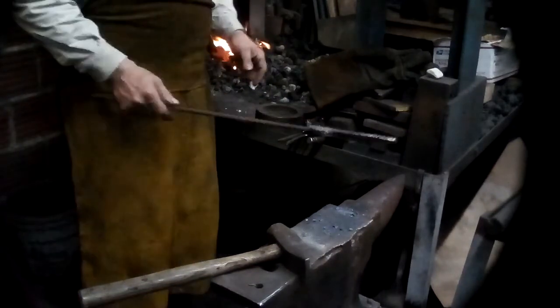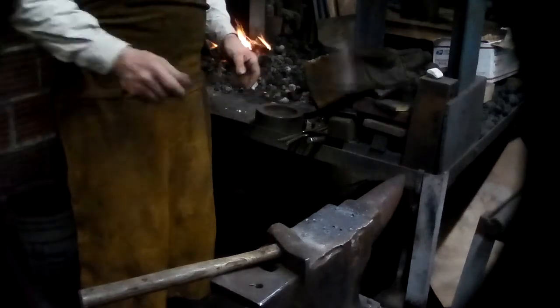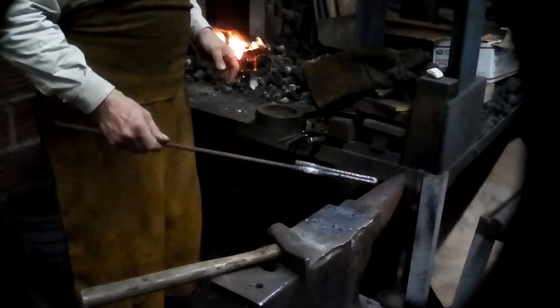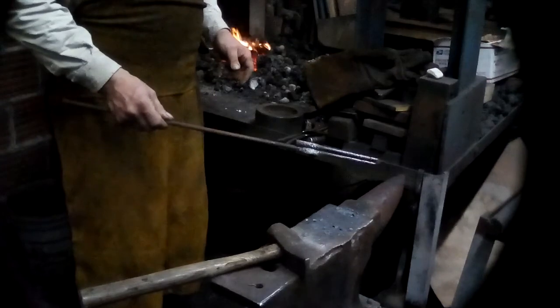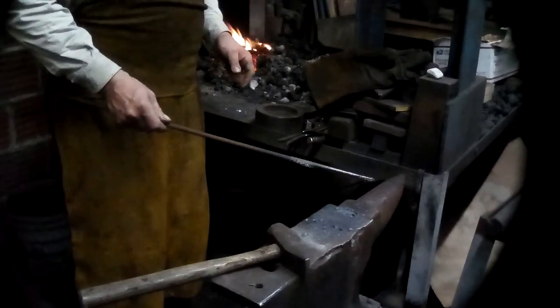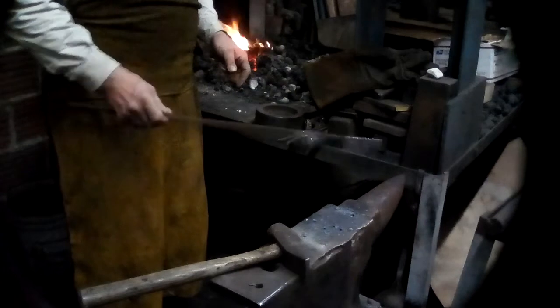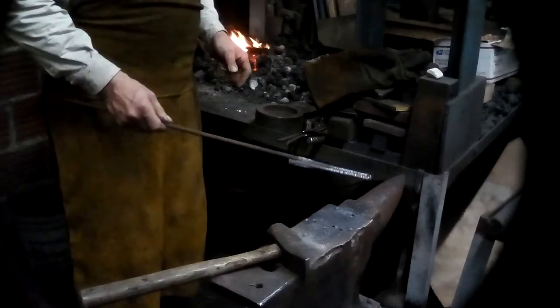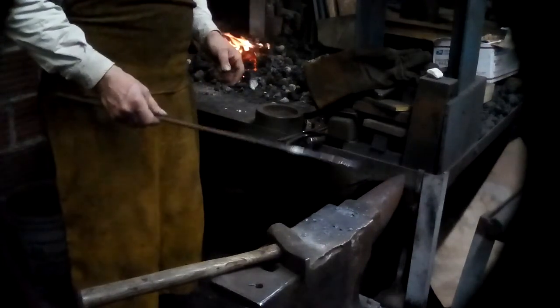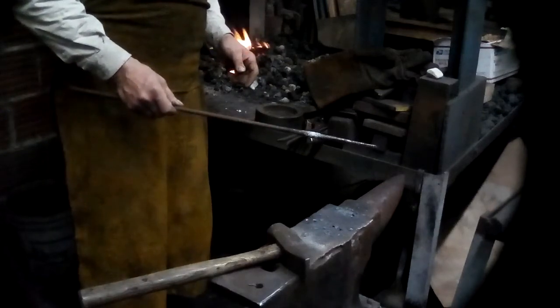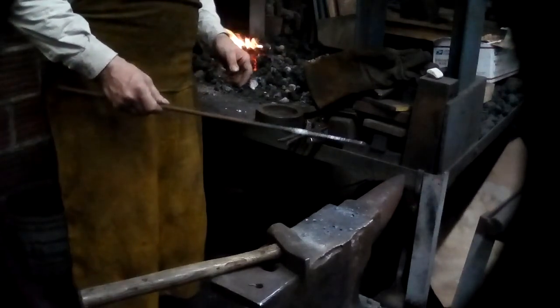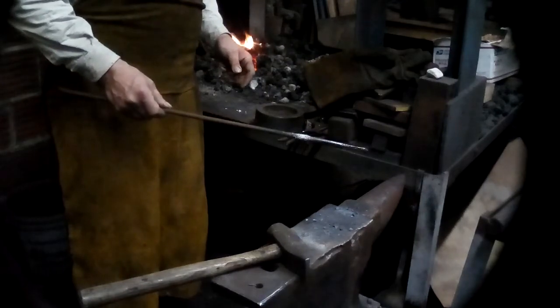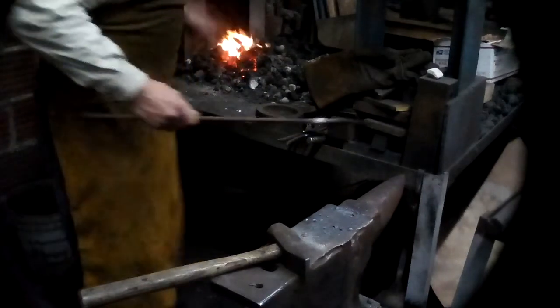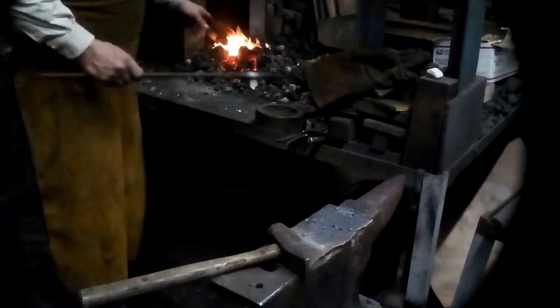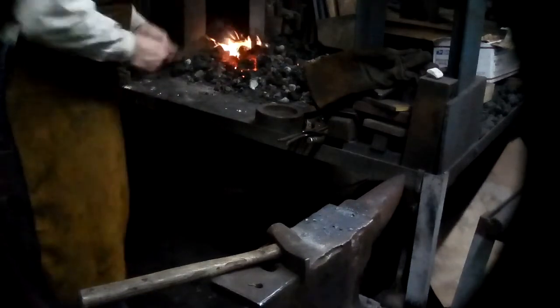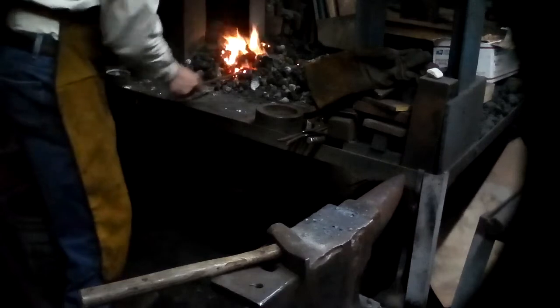Now, I'm using soft coal, bituminous coal that I have coked up. There are an awful lot of people who ask me whether I use anthracite coal at any point. And I have one thing to say about anthracite: it might be something good to heat a house with, but it's horrible forging coal because there aren't enough volatiles in it. It doesn't coke up, so you quite often have a bad atmosphere, because the bituminous coal, the soft coal, as it cokes, has enough volatiles that the atmosphere will protect.